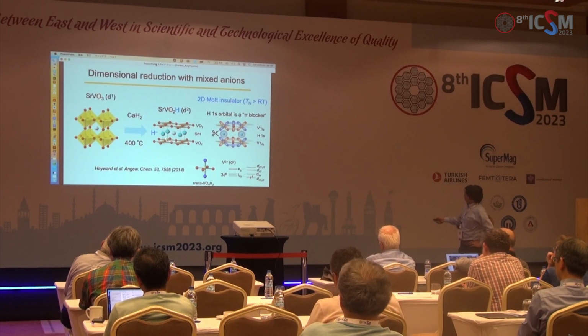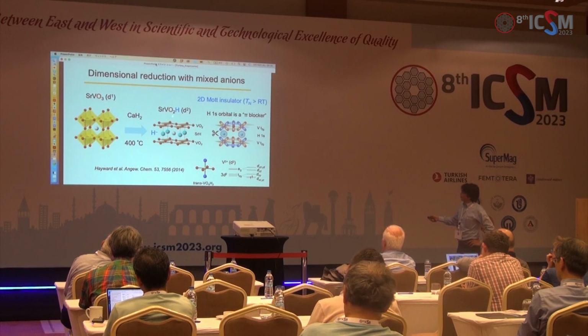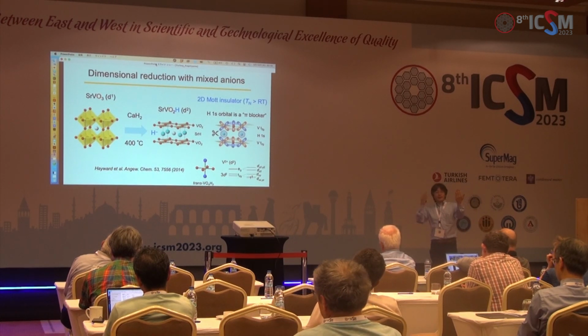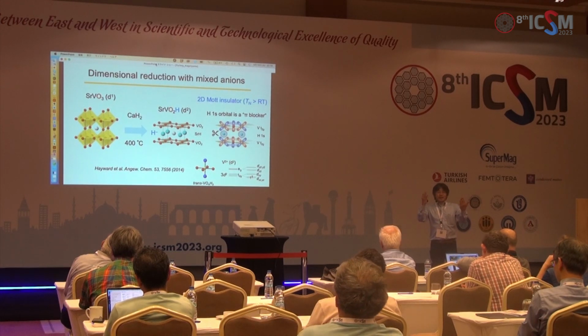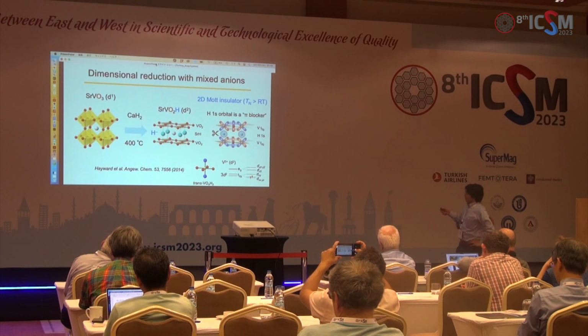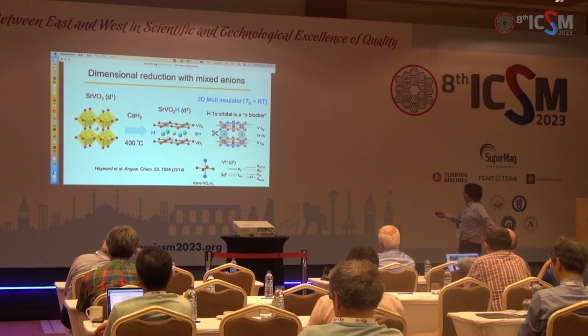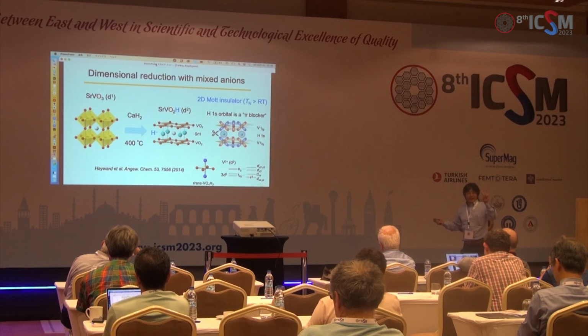And at this temperature, the chemical reaction occurs, leading to this oxyhydride, strontium vanadium oxyhydride. So replacement of the oxygen with hydrogen is a reducing reaction. As a result of the electron donation, the vanadium has carried the d2 electrons per vanadium.